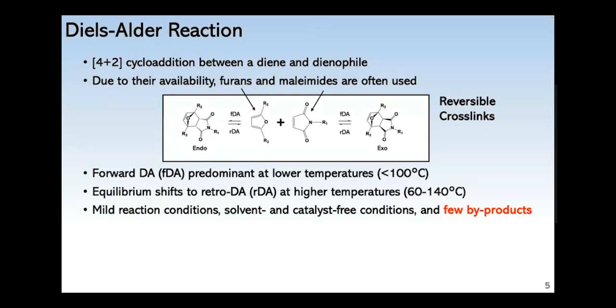So specifically, the Diels-Alder reaction is a type of 4+2 double bond reaction between a diene, such as these furans, and these dienophiles, such as these maleimides, which has the electron-rich 2 double bonds and 1 electron-deficient double bond. And these can produce cycloadducts of 2 forms. One is this kinetically favored endo adduct, and the other one is this thermodynamically favored exo adduct. The endo adduct usually breaks up and forms at lower temperatures compared to the exo.